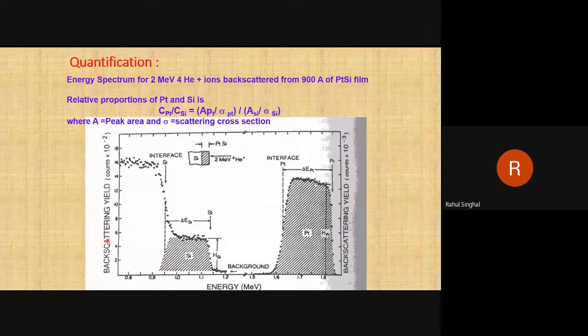So simulation softwares are available. You have some rough idea about the elements present in your sample and their concentration. You just give some values. It will generate a graph like this, like this theoretical one. But the peak positions, heights, and FWHM will not match exactly. You play with the parameters: you change the concentration of silicon, the concentration of platinum, and the thickness of your sample, and you will be able to match your theoretically simulated data exactly with the experimental one. And then you can easily say, okay, this much concentration is present, these peaks are present, and this much thickness is present in my sample.